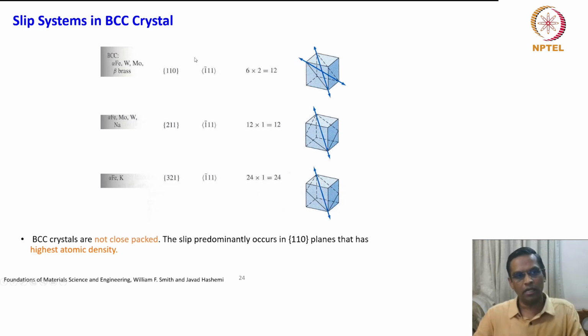And if you go to the BCC crystal, that is the body centered crystal lattice, you have the 110 plane and 111 direction. This type of slip system is displayed by alpha iron, tungsten, molybdenum, beta brass. So they have about 12 systems, and there are other systems. 211 is a plane and 111 is the direction. This slip system is also readily active in alpha iron, molybdenum, tungsten, and sodium. So this again contributes another 12 slip systems.